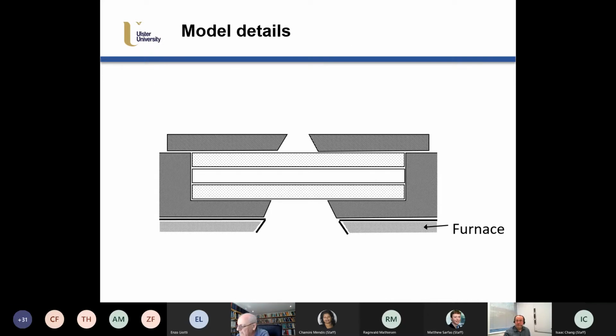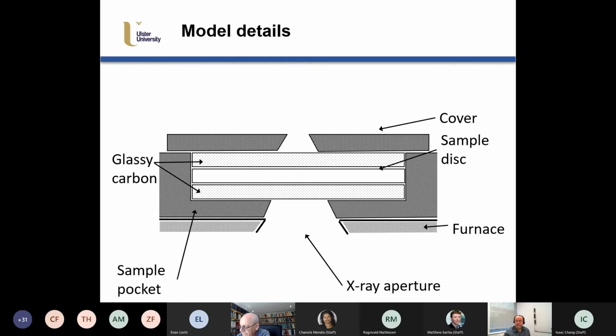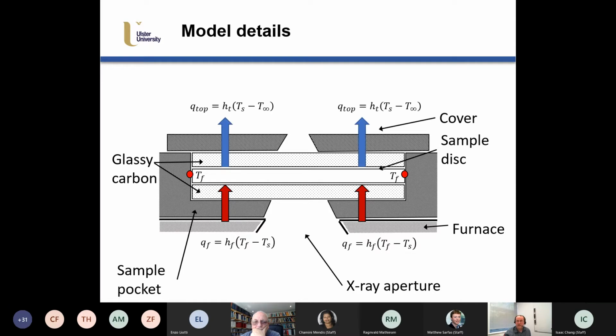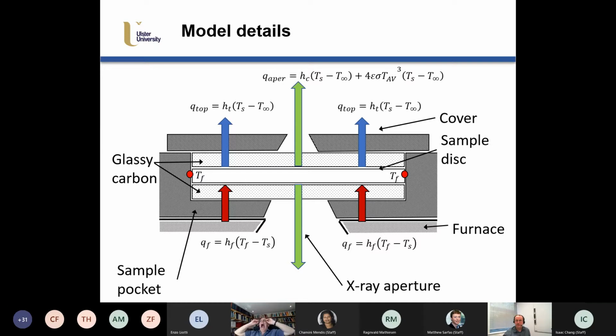So for the model details, we had to replicate this furnace. You have your sample pocket, you have glassy carbon, you have your sample, you have a cover, and then you have this X-ray aperture in the middle, which is conical to account for the diverging X-ray beam going through. We applied the temperature at the boundaries, but we also have more heat input from the outside, from the furnace. This heat transfer coefficient for the furnace is really a tuning parameter, and an important one. You have heat loss from the top, so we estimated what the heat transfer loss would be from the top. And then in the center, you have what I would call a cold finger, where you have both convective and radiative heat losses through the sample, through the X-ray aperture. So this does cause a cold finger effect.